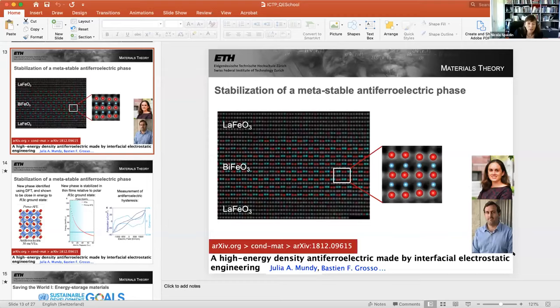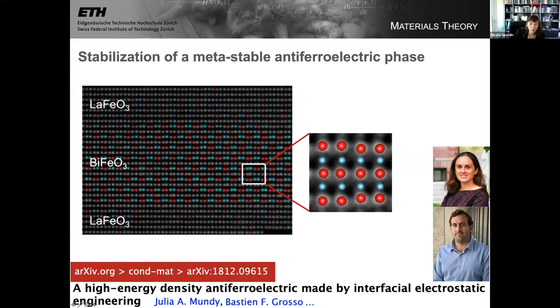This one is not very strain dependent. The experiment has not been done, as this has only been grown on lanthanum, which has a rather similar lattice constant, and a couple of other materials with similar lattice constants. But computationally, Bastian looked at the strain dependence and found that over a reasonable range of strain, it doesn't change its relative energy a lot. So with this particular phase, we don't really want to modify it anymore. We're quite excited to have it as it is. It's fairly robust to moderate changes of strain. But that's absolutely a very good point.